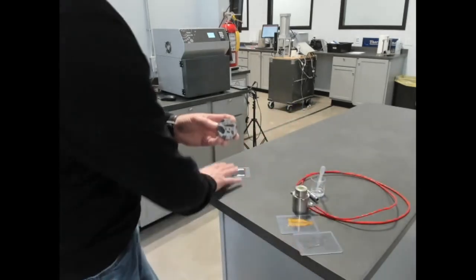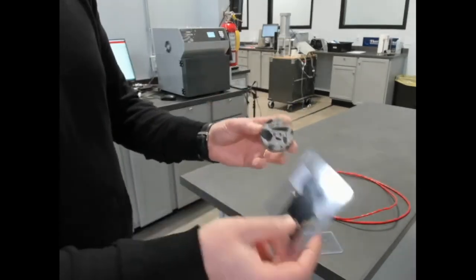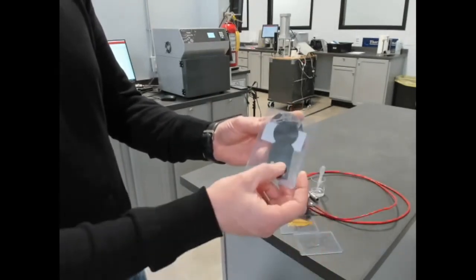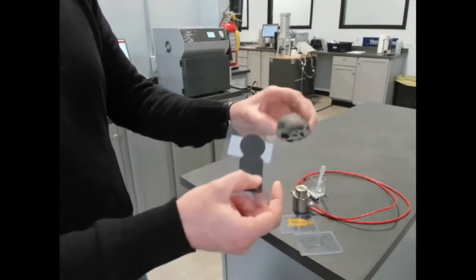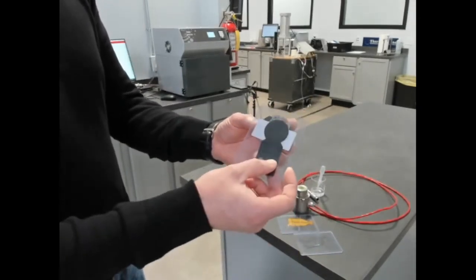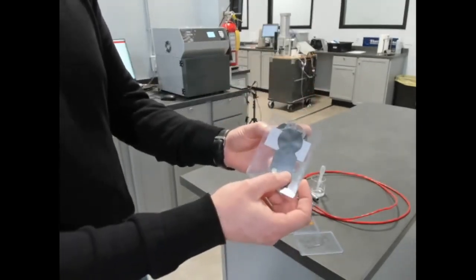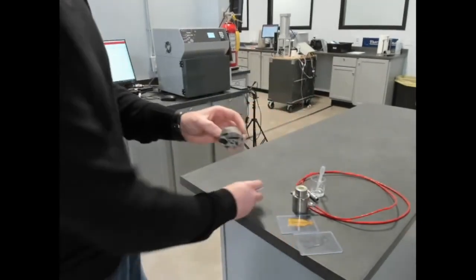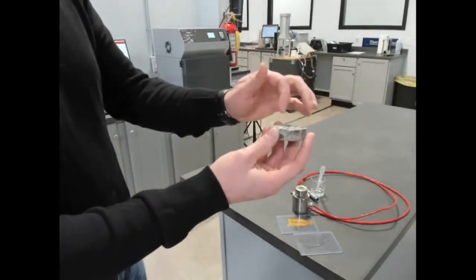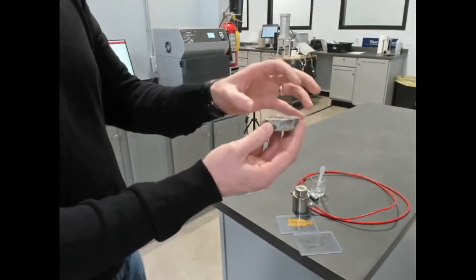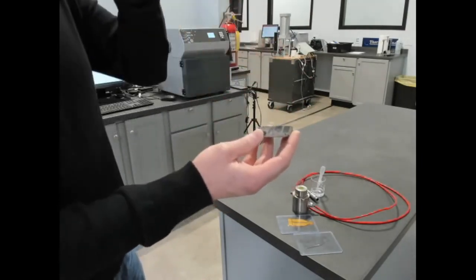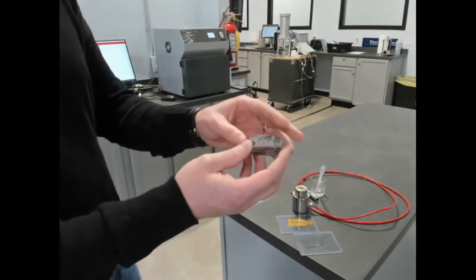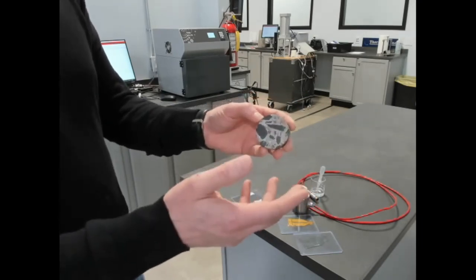So the other strategy is to increase the diameter of the sensor using a TPS. You can see the effect of going to a larger diameter, that you're going to increase the area and get a larger amount of volume included in that data. That does help. But ultimately, for the thermal conductivity of this piece, what is it? The only way to really be confident that you're getting the full sample represented is to measure across the whole surface from one side to the other using a steady state. And then you have the resistance effect. So in the transient measurements, especially with these larger sensors for such a sample, we're doing 10, 20, or 80 seconds.